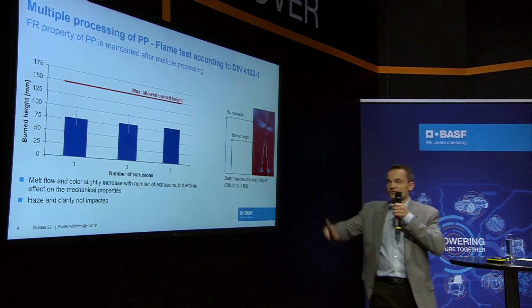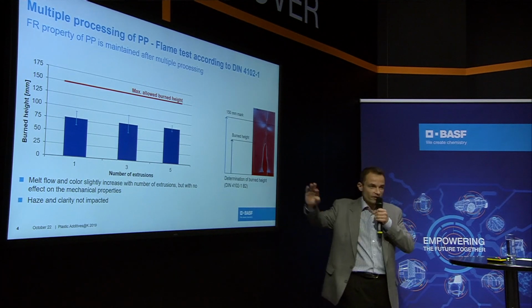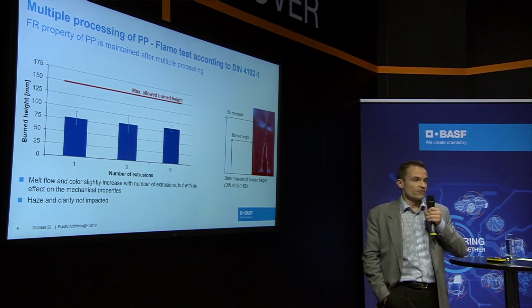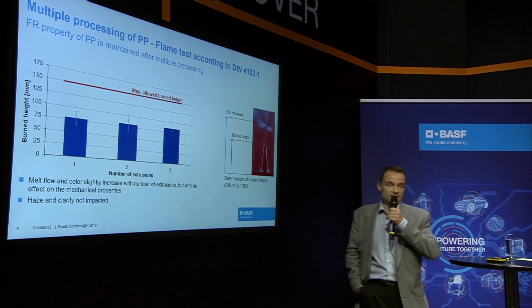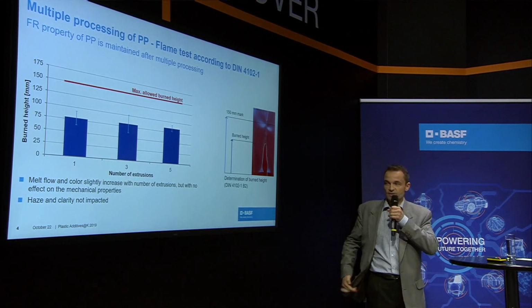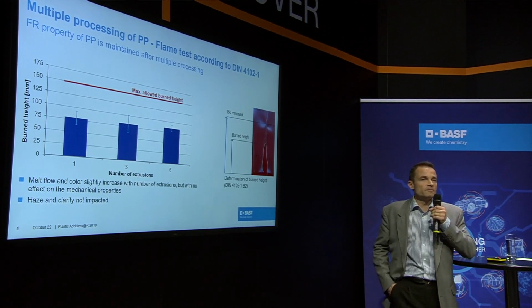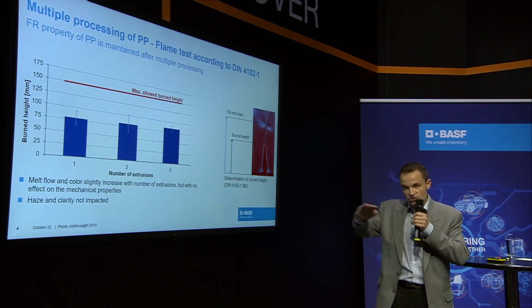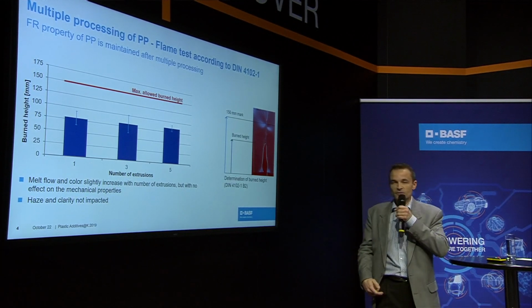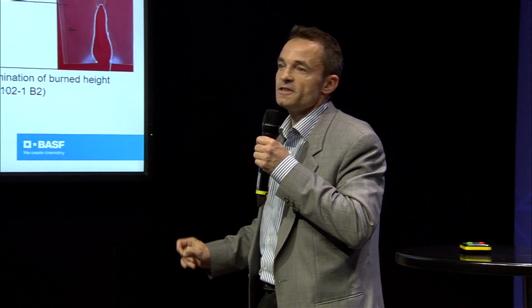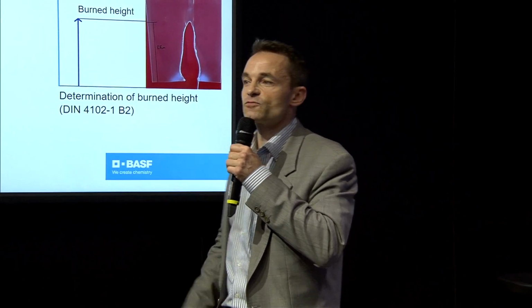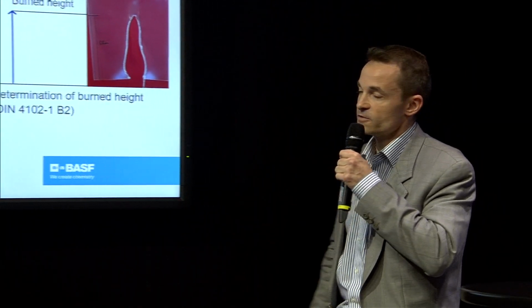You can see on the left-hand side on the graph that after 5 extrusions, the flame retardant performance is absolutely maintained. So it's a nice result. We saw that the melt flow index and yellowing tend to increase over the extrusion, which is normal. But the mechanical properties and the optical properties were nicely maintained. That's important.